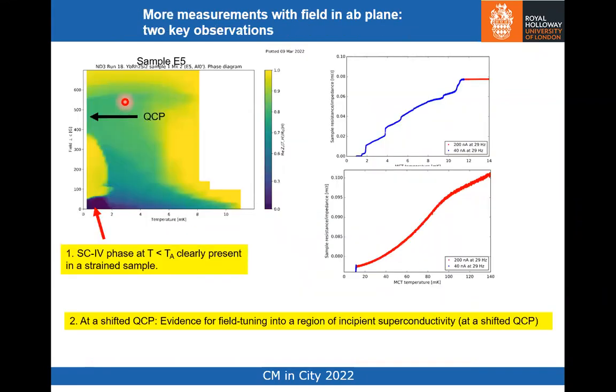So what we were keen to do, this relates partly to the question, is to explore samples with field in the AB plane out towards the quantum critical field. Now, for one reason or another, the sample that we had was relatively thin and more subject to strain effects.